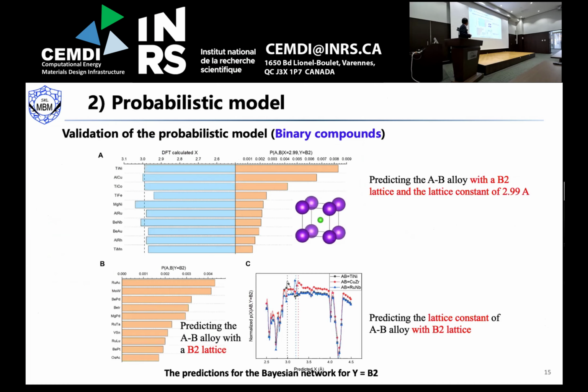So this is for the B2 structure. If we know the B2 structure and the lattice constant, from our method we can predict the top 10 alloys which fit these properties. NiTi is a well-known alloy, but not all of them are shape memory alloys. And also, if you only use the B2 lattice, we can also use our method to predict the top 10 alloys. And once you know the crystal structure and the elements, you can also predict the lattice constant. This is for the B2 structure.